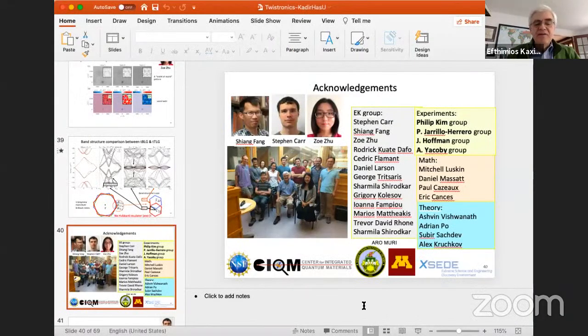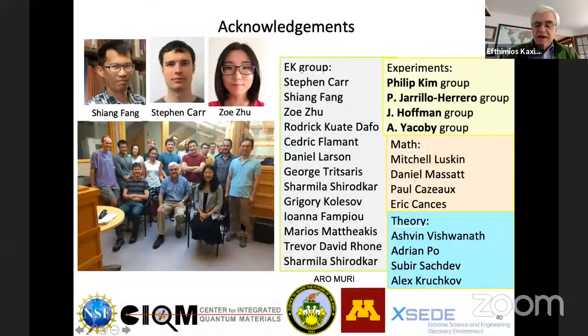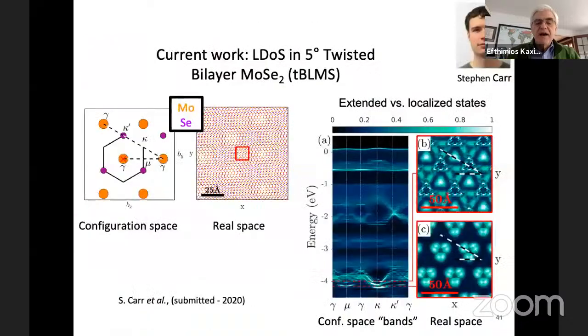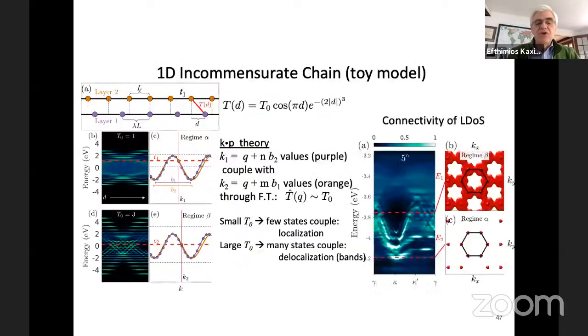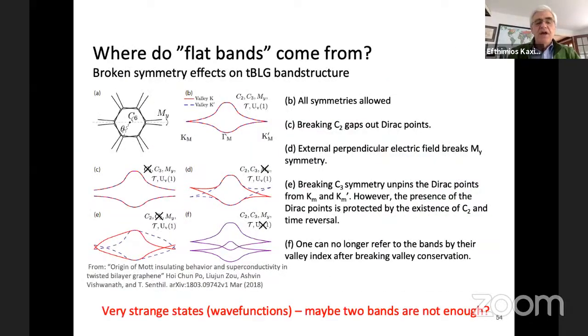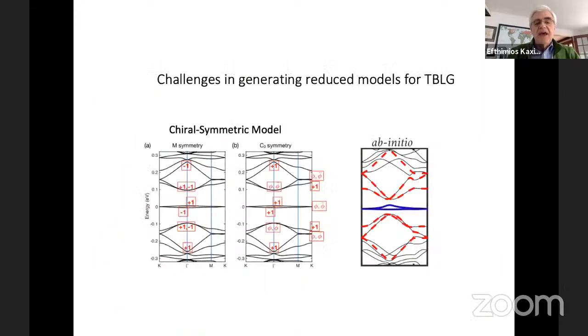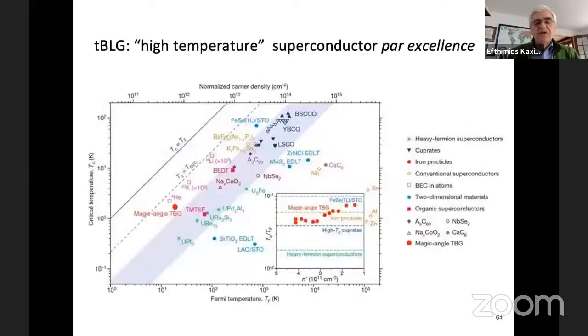Let me, if you allow me, share my screen again. I wanted to show you something interesting. I had another picture that, by the way, let me just show you this very quickly. So this is molybdenum diselenide, one of the types of materials that you just mentioned. And you see a similar type of behavior, localized states here and bands and so on, by doing this kind of twist. So this is at a 5 degree twist, which is easier to achieve and therefore more promising. And there's another thing that I want to show you. The actual temperature is indeed low, and you can't change that temperature easily because it's controlled by the intrinsic interactions.